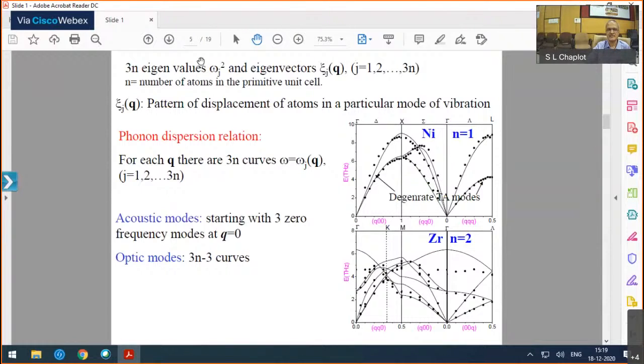So if I know the elastic constant, I can calculate the slopes, and if I know the slopes, I can predict the frequencies, at least near the origin of the Brillouin zone. At least the linear part of the acoustic phonons is very easy to predict, and so one can make measurements to confirm those values, and then whatever temperature or pressure dependence one might be interested in.